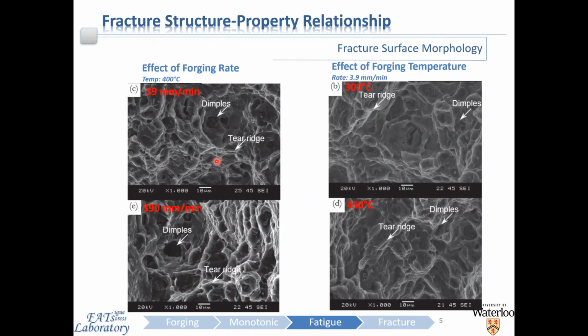The fracture surfaces of all samples were characterized by a terrace-like faceted morphology with an intergranular fracture path as in the as-extruded condition, whereas the forged conditions exhibited a much more dimple-like fracture surface and transgranular fracture path indicative of more plasticity, as can be seen here.